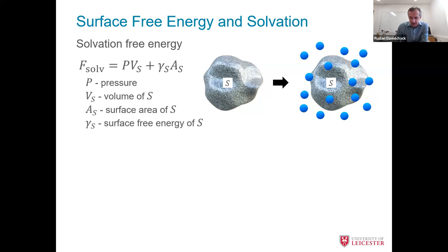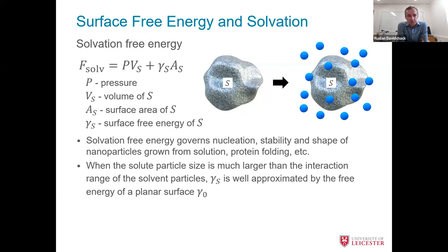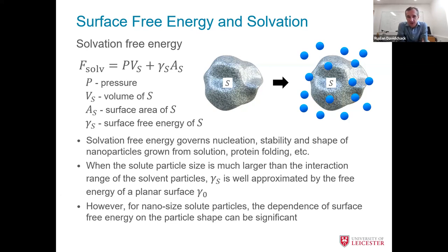Solvation-free energy is related to nucleation, stability of shapes of nanoparticles grown from solutions, protein folding, and so on. This is something that in molecular simulation and in experiments is quite important. When the particle is very large, every wall eventually, at a small scale, becomes flat. So you could try to approximate gamma-S with gamma zero, which is the free energy of a planar surface. But that approximation is rather crude for small particles like proteins or nanosize particles.